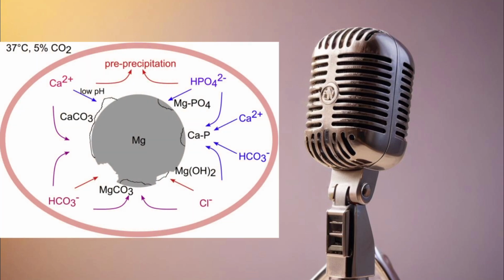But process modifications can influence porosity, affecting both corrosion rates and cellular interactions. Some LPBF fabricated magnesium materials, as you saw in the table, exhibit rapid degradation, which can compromise their structural stability. This is evident in LPBF pure magnesium, which demonstrates significantly accelerated corrosion rate compared to its cast counterpart. And corrosion resistance of LPBF fabricated WE43 alloy is lower than the cast version, with increased degradation due to microgalvanic reactions between stable oxide particles and the magnesium matrix.